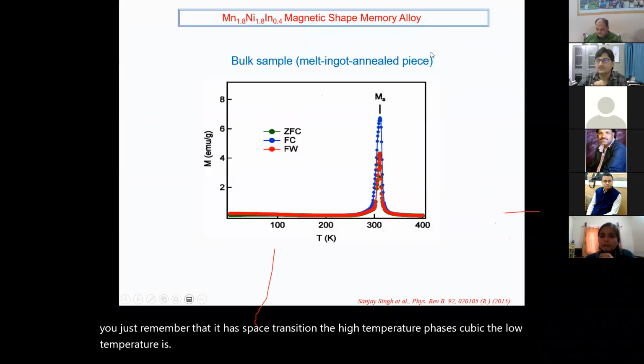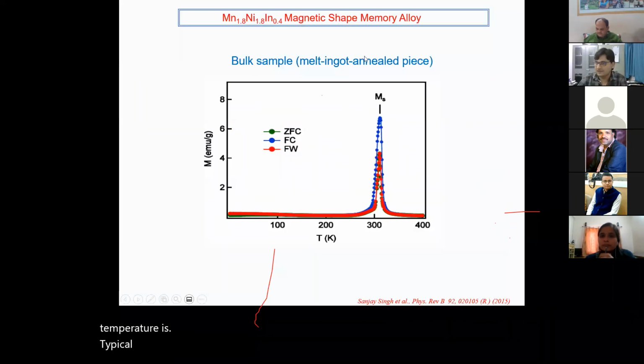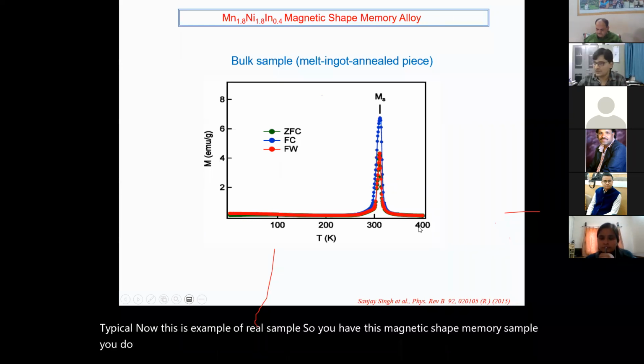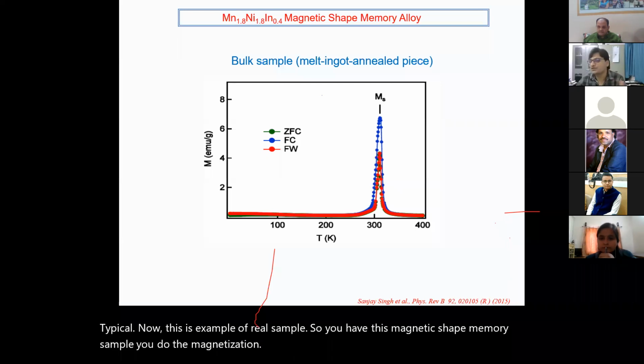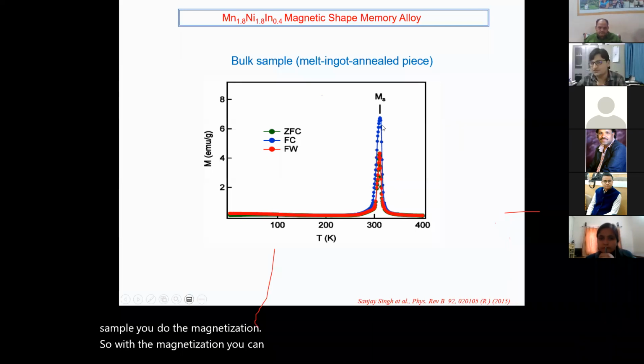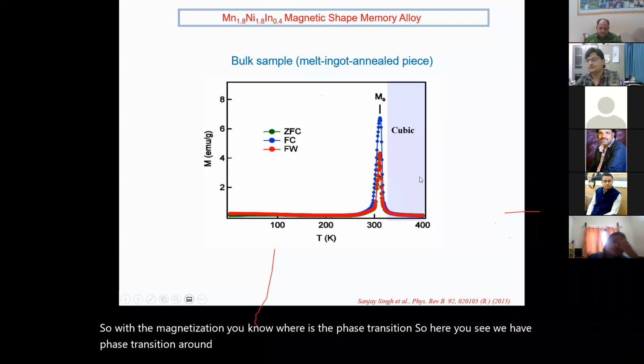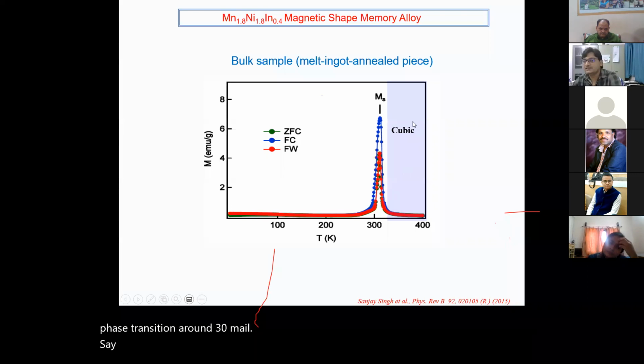Now, this is an example of a real sample. You have this magnetic shape memory sample. You do the magnetization. With the magnetization, you can know where the phase transition is. Here you see we have a phase transition around 300 K, which means at high temperature it must be cubic, and the tetragonal phase must be at lower temperature.